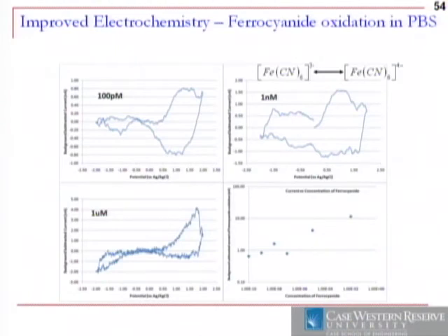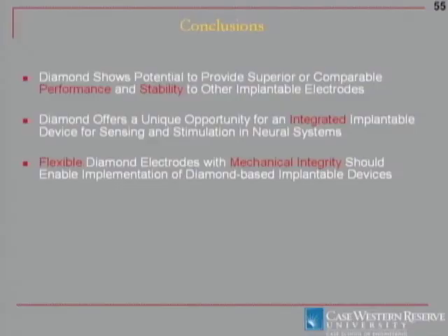The net result, and this is the final piece of data shown, is we now can use this for electrical sensing. This is a microelectrode, so we're able to do fast scan voltammetry. And this is not dopamine yet. This was a standard redox couple down to 100 picomolar using ferrocyanide oxidation in PBS. And so now we're back down to the levels we wanted to be at originally with our microdisc electrodes, and we're going to move to dopamine detection of neurochemical recording.